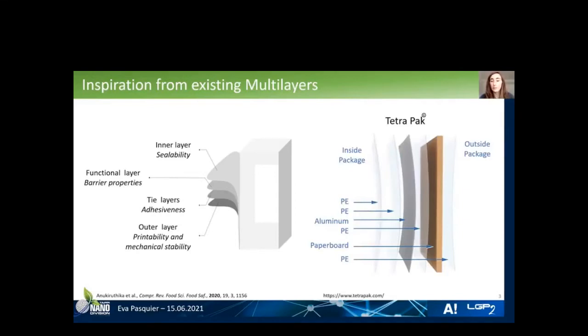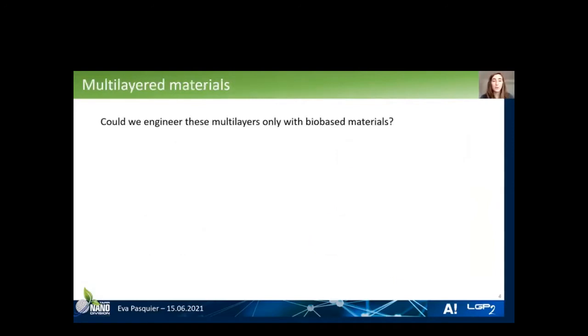So it has, for example, paperboard as the main component that is there for the mechanical properties, and aluminium for the barrier and light barrier properties, and also several polyethylene layers. Some of them are there for the water barrier, but most of them are there only as a tie layer, for adhesion purposes. So how could we reduce the number of layers and maybe increase the bio-based amount in this kind of material? What we have engineered is only based on bio-based materials.